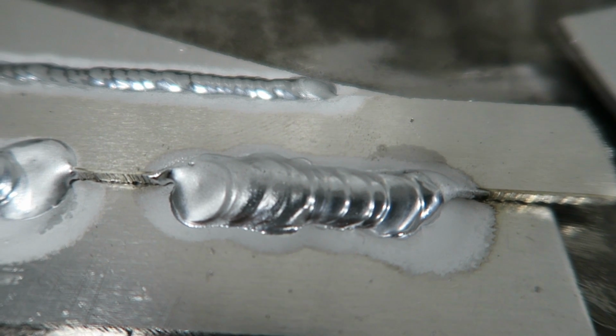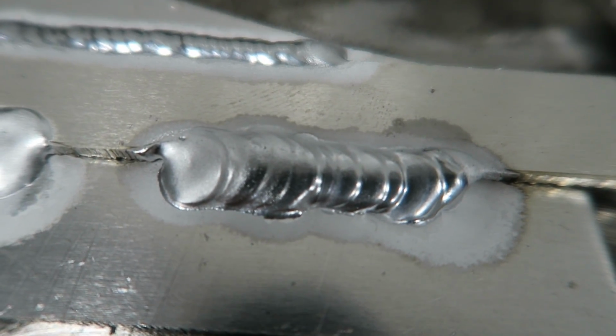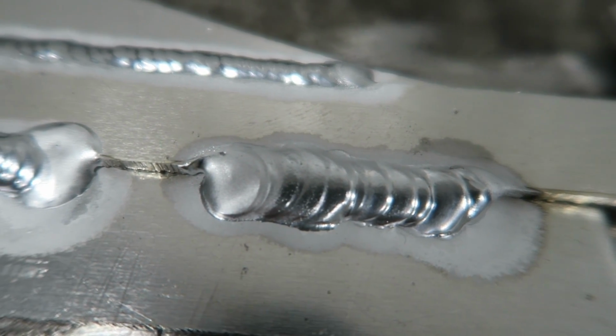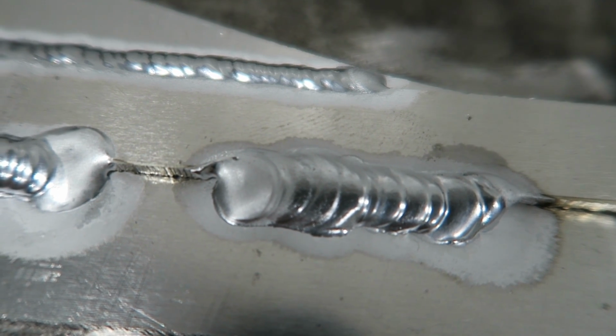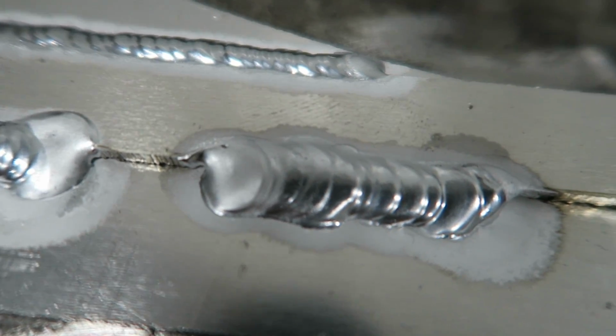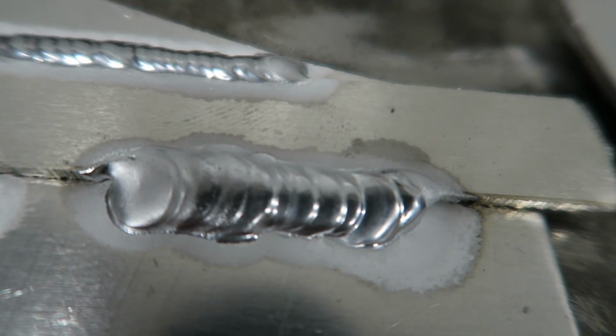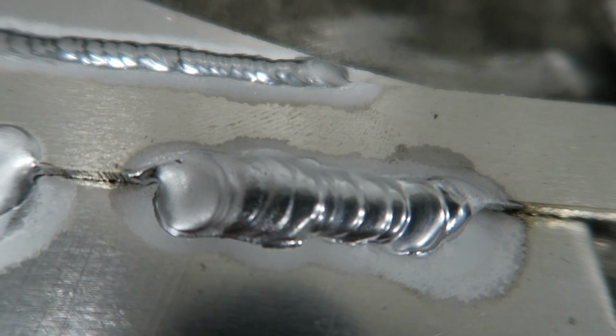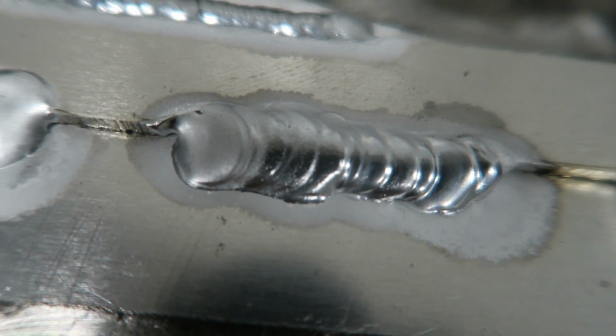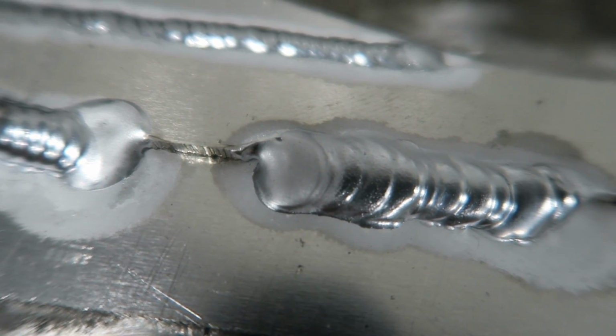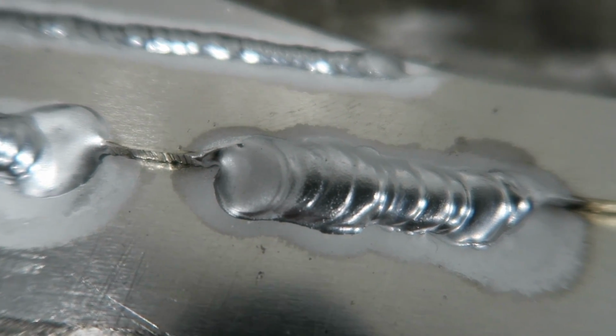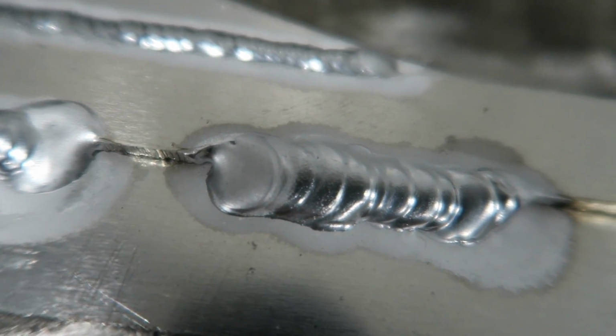Now, 3 and 4. This weld, a little bit less heat, a little bit thicker filler rod. Again, puddle all over the place. Everything's all over the place. We had too much heat in the part. The bead was jumping outwards. It fanned out at the end. Again, this piece was hot now. We're only running about 60 amps. And you can see how uncontrollable that bead was.